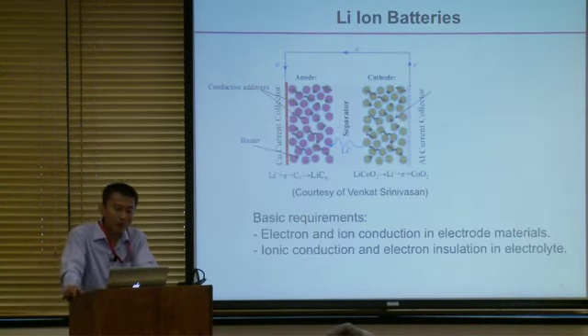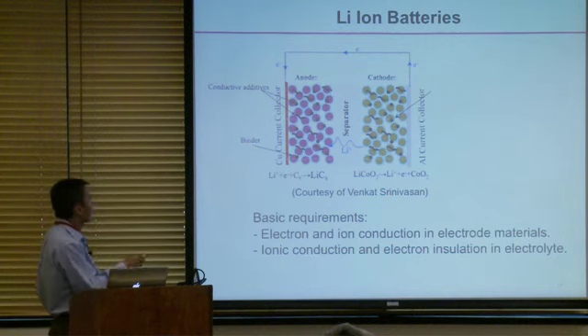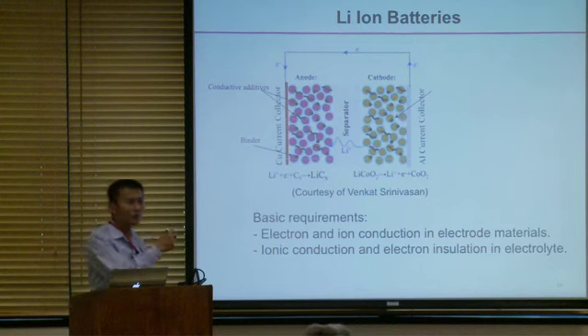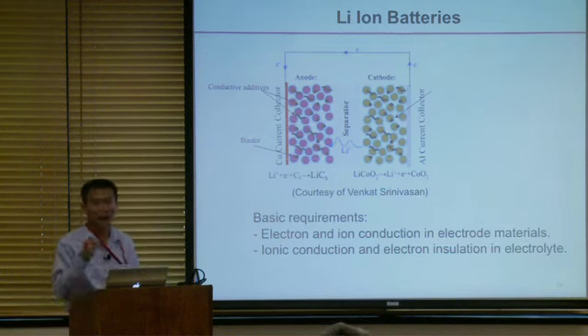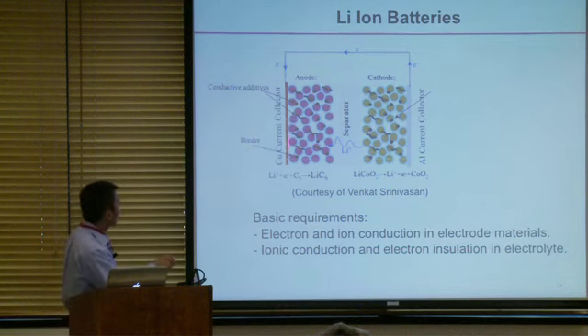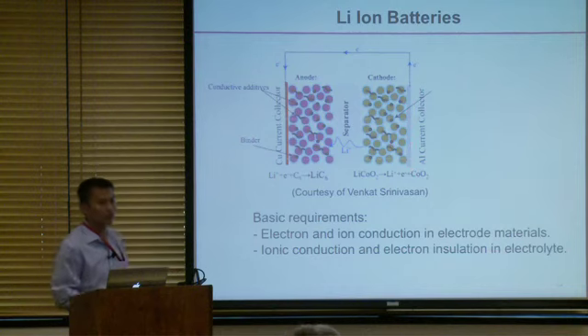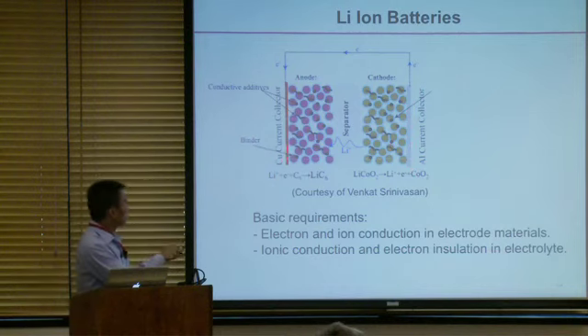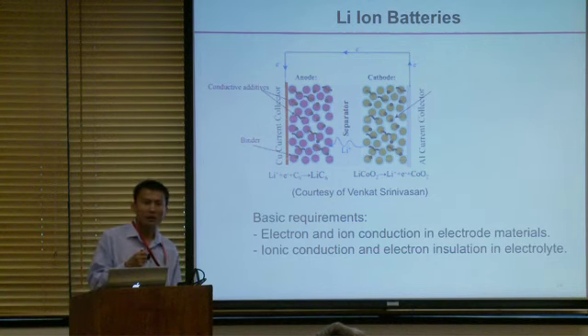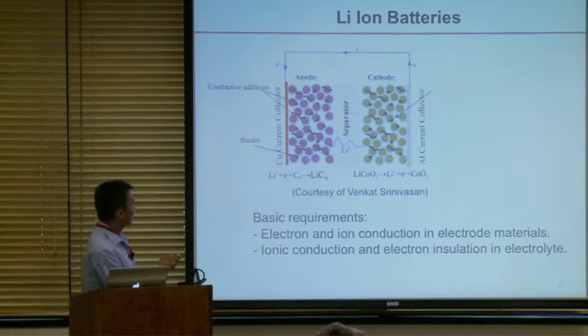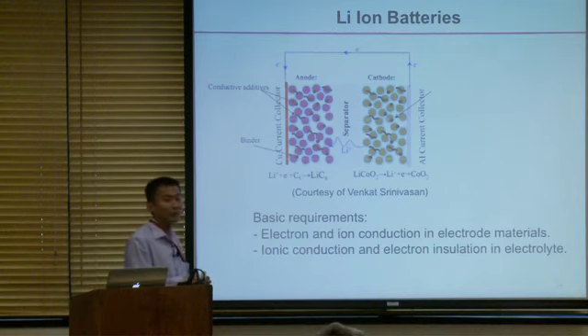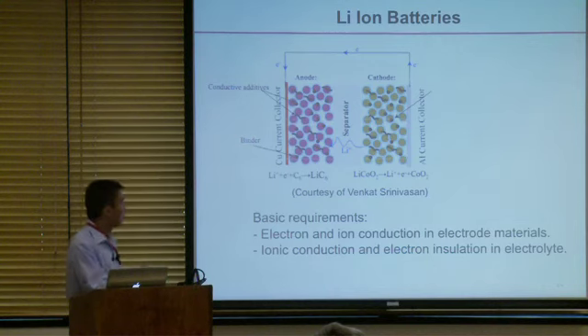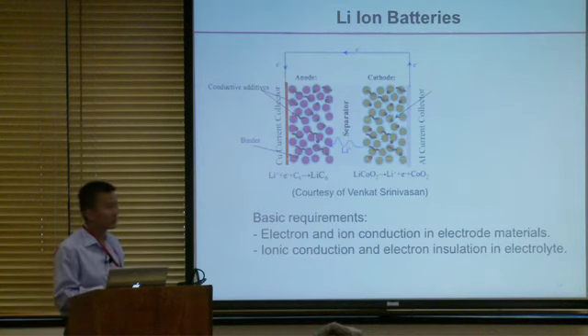Now let's look at lithium-ion batteries. This is a basic structure of lithium-ion batteries. Now this comes to the real structure. There's a lot of details inside, and every detail matters. This is the negative electrode side. This is the positive electrode. Typically, you use a foil of metal, in the order of, say, 10 micron thick only. And then you put the carbon particles on the negative side onto this metal foil. This is copper. There's a special requirement for why it's copper and not aluminum: aluminum reacts with lithium at a low voltage. So what exactly is the foil you choose also matters.